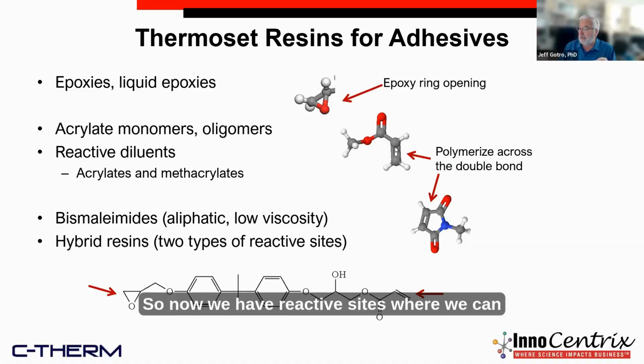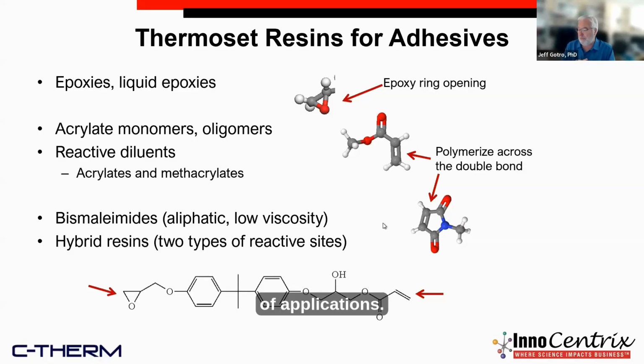So now we have reactive sites where we can polymerize across these double bonds, and we can make them go very, very fast. So these are what are called free radical polymerizations. And you can initiate a radical, and then they propagate very, very quickly. So this is how you can get systems that cure very quickly within a matter of minutes.